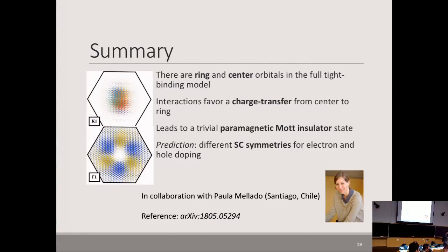So there are two ways if you have such a difference in the real space structure of a band. This is before talking about the orbitals. If you have such a difference in how the structure looks, there are two things you can do. There's what you suggest, which Oscar is actually going to talk about, which is indeed Wannier functions that are larger than your unit cell, in which you can create a difference between K and gamma points by having cancellations between different phases and so on. That's one way of going about it. The other way is that you can say, well, there are actually two orbitals which are hybridized, in which case we just literally wrote down a model that has exactly these spatial structures as you can see them in the real space tight-binding model.